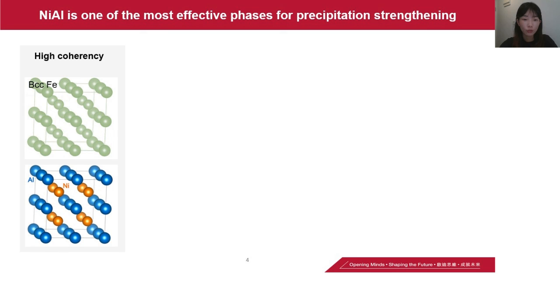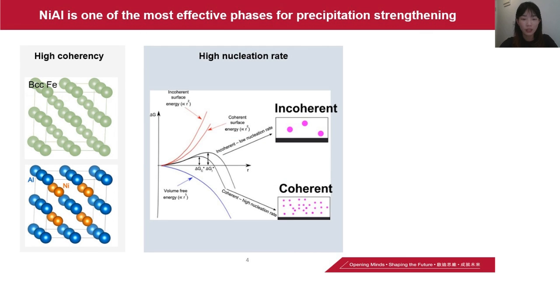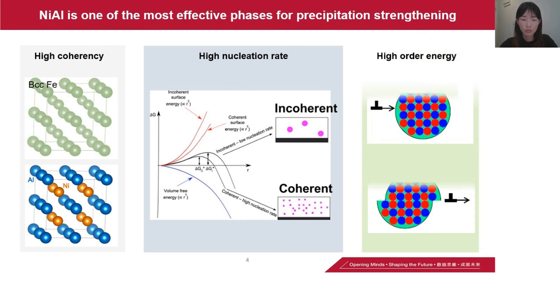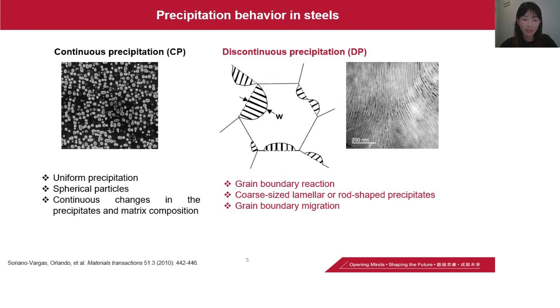Nickel-aluminum has a B2 structure with a lattice parameter close to that of BCC iron. The high coherency results in a decreased interfacial energy for nucleation, thus the nucleation rate increases, leading to the formation of high number density nanoparticles. And nickel-aluminum has high antiphase boundary energy, which can contribute to the high strengthening effect.